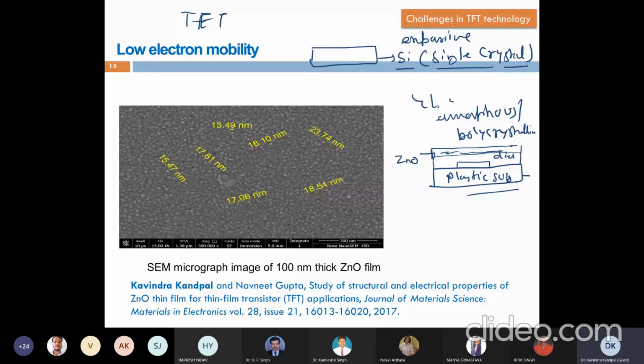So what happened? You can clearly see this is one of the 100 nanometer thick ZnO film SEM images, which we did during our experimentation. You can see within there are the grains. Within the grains, the structure is single crystalline, and after the grains, these are the grain boundaries. Grain boundaries are like this: you are roaming on a highway, and the highway is such that within every 500 meter distance, there is a big speed breaker.